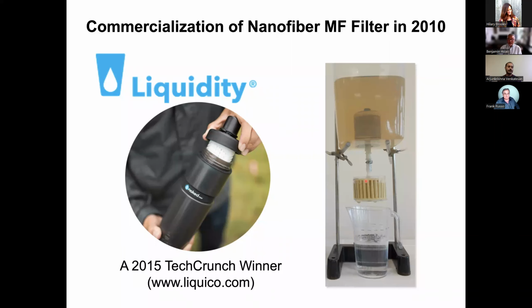And with this technology, we actually spun off two different startup companies. One is called Liquidity. They produce a membrane in between ultrafiltration and microfiltration. But since the porosity is so high, over 80%, the flux is very high. So they can actually use gravity to remove most of the pathogens with a particle size larger than 0.2 microns. In addition, we can also use the surface to absorb some of the chemicals. So this startup company is actually making something very similar to LifeStraw. It's much cheaper and the flux is higher. And this company's product, Naked Filters, won the TechCrunch 2015 award.